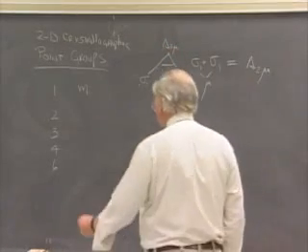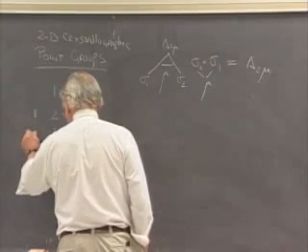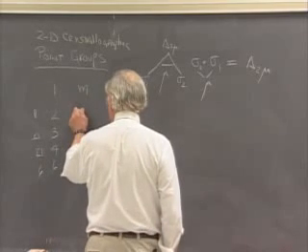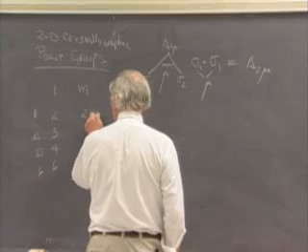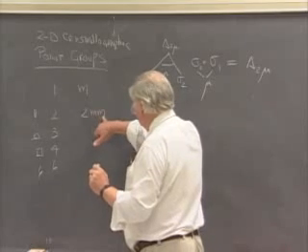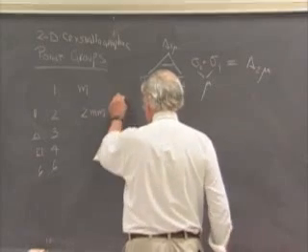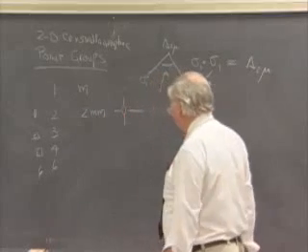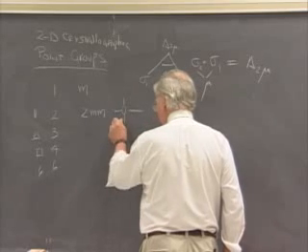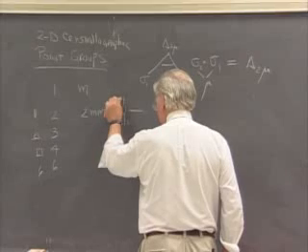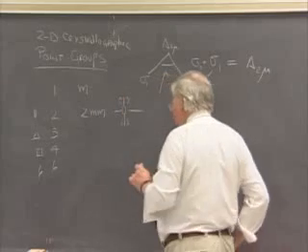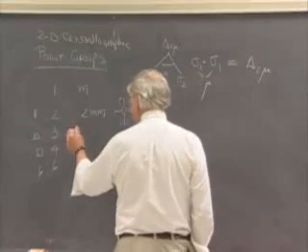That let us, in addition to a one-fold axis, a two-fold axis, a three-fold axis, a four-fold axis, and a six-fold axis, combine reflection with these axes to get symmetry combinations that we named according to the symmetry elements which were present in the final combination. We used two mirror planes if the mirror planes that arose were independent in the sense that the two-fold axis never turned one into another, and independent in the sense that if we draw a representative motif, the way those motifs were disposed about one mirror plane was different from the way they were arranged about the other one.